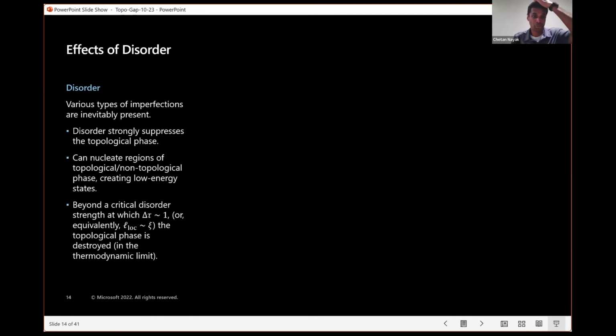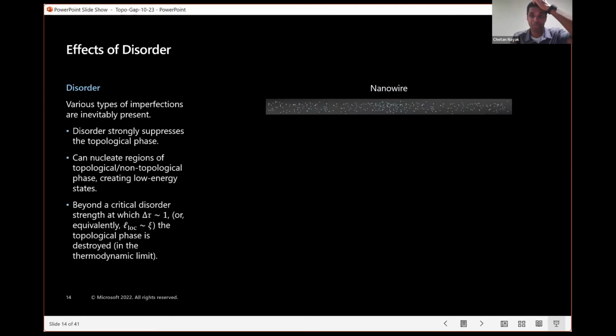Now we have to consider disorder. So there are various types of imperfections that are inevitably present. There's going to be all kinds of disorder in our nanowire. As a result of that random potential, an electron going through the wire will bounce around all over the place. The disorder strongly suppresses the topological phase, and it can nucleate regions of topological and non-topological phase, creating low energy